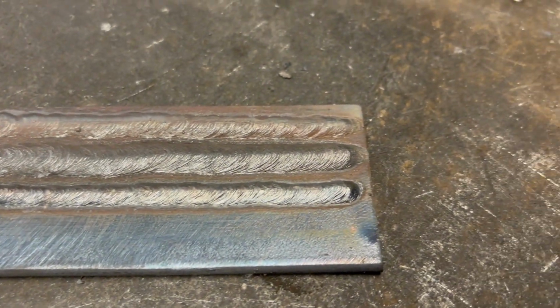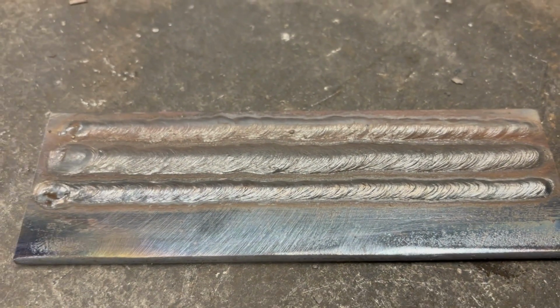And now we're going to see what happens when we drop our amps down to 125 and travel a little bit too fast. You'll notice the bead is going to become narrower with the ripples less defined, and there's a higher chance of lack of fusion with the weld sitting proud on the plate. This really shows how heat input and travel speed are crucial for producing a good weld. Here you can see the difference between all three runs and how narrow and proud our last weld has become compared to the others.